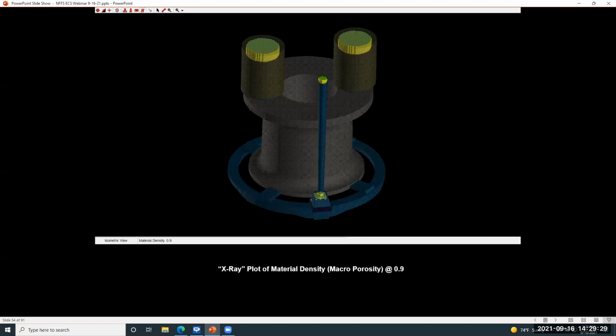This is an X-ray plot, or what we call an isosurface plot. We're plotting material density, which is our predictor of macro porosity or shrinkage. We can see the piping in the risers, and the fact that by using the sleeves, that slows down solidification, and we can see the piping. We can also see some shrinkage in the sprue and at the base of the sprue. This is at a value of 0.9. In other words, nothing is shown unless that area has lost 10% of its nominal density.